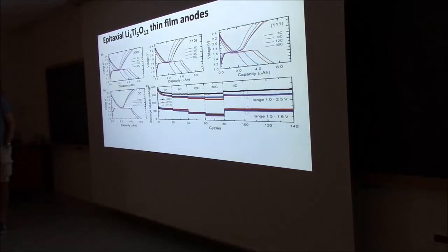If I look at the full range between 1 and 2.5 volt, then it depends very much on these tails as well. And then you can see that the 100 orientation is higher than the other two. But that's the moment where you also are looking into the lithium stored at the surface. And the 100 had these pyramids formed, so there is a much higher surface area, and that explains this difference. So it's not so much the crystal structure itself, it's only how much surface you have available for the material to attach.